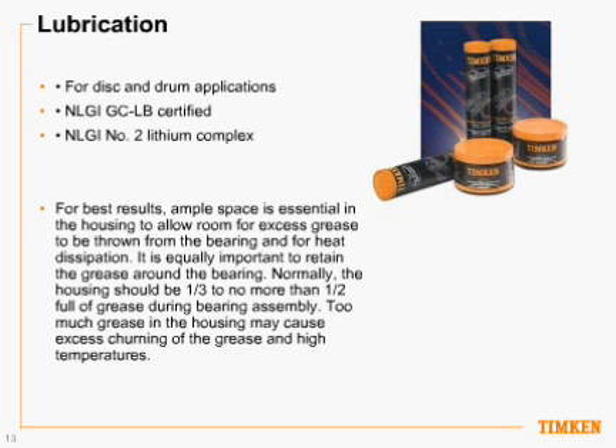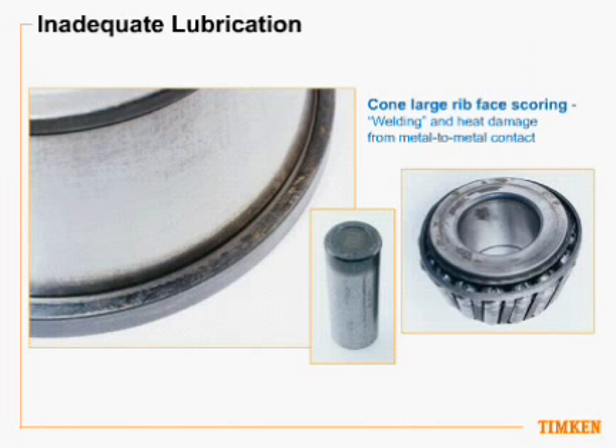Okay. So for best results, ample space is essential in the housing like we talked about, to allow room for excess grease to be thrown from the bearing and for heat dissipation. These bearings are like mini pumps. As they rotate, the grease is pumped from the small end to the large end, so you need a little bit of room in there for the grease to move around. It's equally important to retain the grease around the bearing. Normally the housing should be one-third to no more than half full of grease. Too much grease in the housing may cause excess churning of the grease and high temperatures.